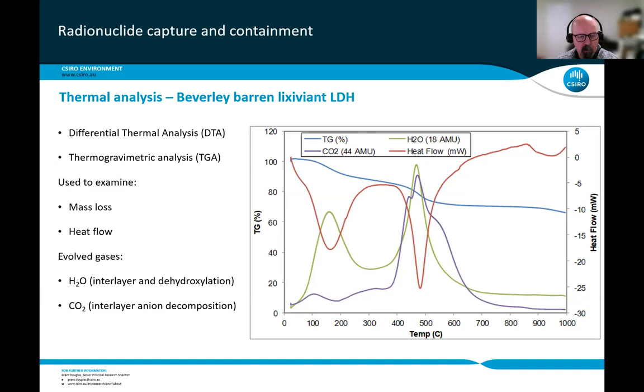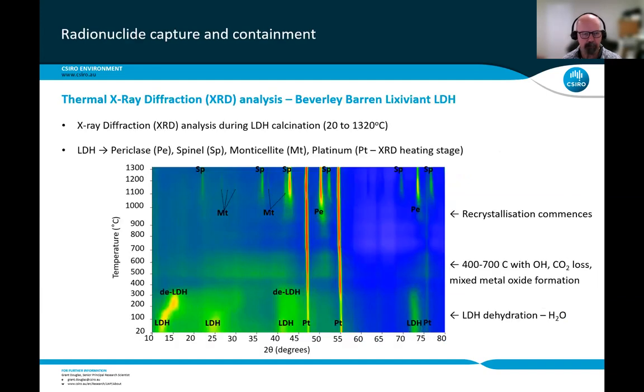So you then start to lose more waters and you start to form what's known as a mixed metal oxide. But coincident with that loss of water that peaks around about, say, high 400, almost 500 degrees, you also have loss of CO2. And that CO2 was the carbonate and bicarbonate that was originally present as anions in the layered double hydroxides. And then above about, say, 600 or 700 degrees, not much more happens. But you've pretty much decomposed everything up above around 600 degrees in terms of loss of water, loss of CO2, and conversion of the layered double hydroxide to a mixed metal oxide.